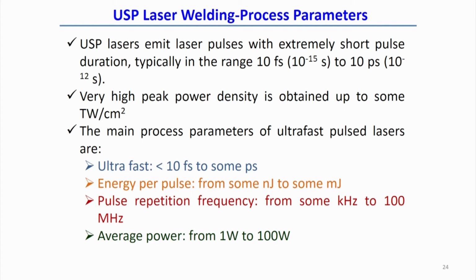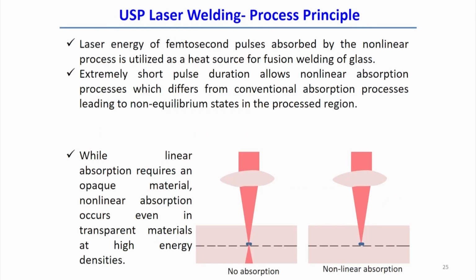So, there is a wide applicability of this ultra short pulse laser nowadays in both metallic and non-metallic materials. Average power varies from 1 watt to 100 watt. So, average power is quite low as compared to other high power or conventional laser processes, but the significant point in ultra short pulse laser is the very high peak power, and the application of the pulse energy over a femtosecond duration. So, definitely there is some characteristic difference with the application of the ultra short pulse laser, which cannot be explained by or applied to the conventional laser welding processes.